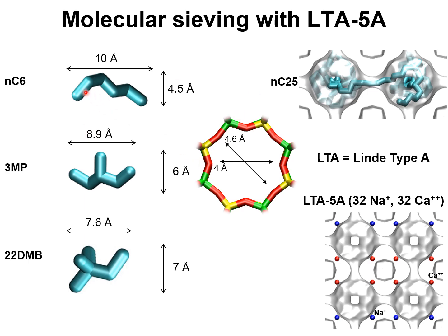It is possible for a linear molecule such as hexane to diffuse easily or relatively easily through the 8-ring windows of LTA-5A zeolite, whereas the monobranched isomer and the di-branched isomers are limited in their ability to hop from one cage to the adjacent cage because the dimensions of the molecules prevent the intercage hopping.